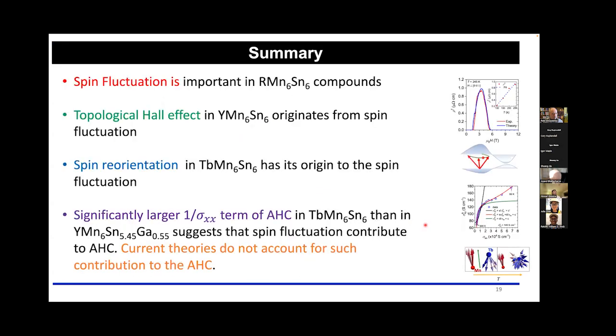So that's all about my talk. So again, the summary or the conclusion is that spin fluctuation is important in 166 compounds, especially when we start putting the magnetic rare earth elements into the system. Topological Hall effect in yttrium manganese 16.6 originates from fluctuation. Spin reorientation in terbium manganese 16.6 has its origin in the fluctuation, and this significantly larger 1 over sigma XX term of AHE in terbium manganese 16.6 than in the yttrium compound suggests that spin fluctuations do contribute to AHC, and that this is the term that's currently not in theory.